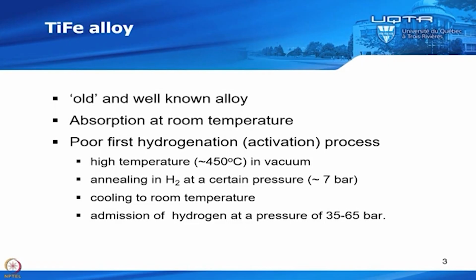So first, let me talk about iron titanium alloy. This is an old and well-known alloy. This was discovered as a metal hydride in the 1970s. It could absorb hydrogen at room temperature, but the first hydrogenation, what we call activation, is very difficult. So even if the alloy could absorb hydrogen at room temperature, usually for the first hydrogenation, you have to go to high temperature, like 450 degrees C